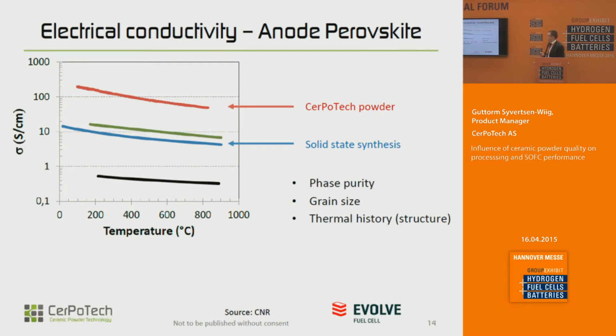Another example is strontium titanate doped with lanthanum, where you have a huge effect on the conductivity. The spray pyrolysis powder has about one order of magnitude higher conductivity than similar or the same material made by solid state synthesis. Here also the picture is maybe not telling the whole truth, because for these materials the thermal history is very important, because the defect chemistry depends on whether you have exposed the material to a reducing atmosphere or an oxidizing atmosphere.